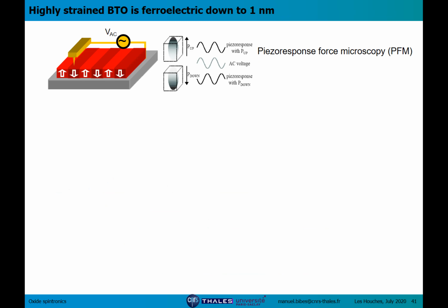So first, when you work with ferroelectric tunnel junctions, because the barium titanate ferroelectric is very thin, because it has to be compatible with tunneling, you want to make sure that your ferroelectric is ferroelectric, okay? Because just like for ferromagnets, when you decrease the thickness of a ferroelectric, ferroelectricity tends to be weakened and eventually disappear at very low thicknesses. So to test ferroelectricity, we use a technique called piezo-response force microscopy, which